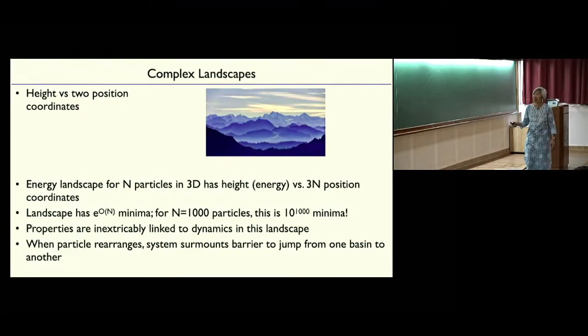So this is a nice landscape, right? But it's the height versus two position coordinates. Of course, we're talking about a landscape which is the energy or the free energy in a 3N-dimensional coordinate landscape, 3 dimensions times N particles. So this landscape has of order e to the N minima. That's huge, okay? Even for 1,000 particles, that's about 10 to the 1,000 minima. And so it's incredibly difficult to map out.